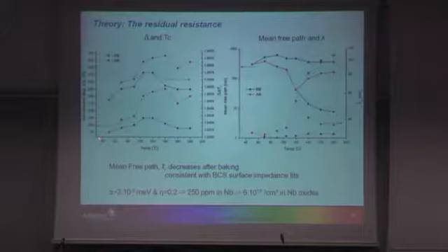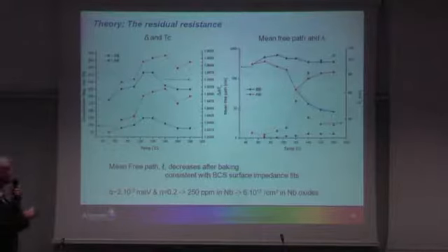And we can extract some parameters: concentration of magnetic impurities, in dotted line with the squares here, versus baking temperature, and delta over kTc on this scale here, which is around squares, versus temperature. So in black is before baking, so the baseline. In red is after baking. We can see that delta over kTc increases after baking. That was found also when fitting with BCS theory.